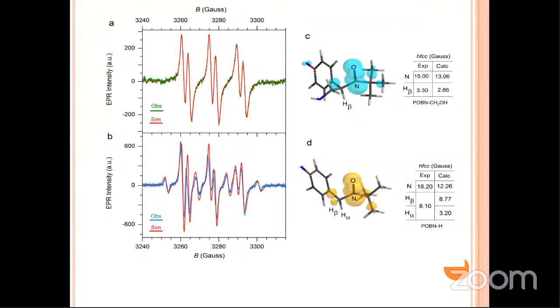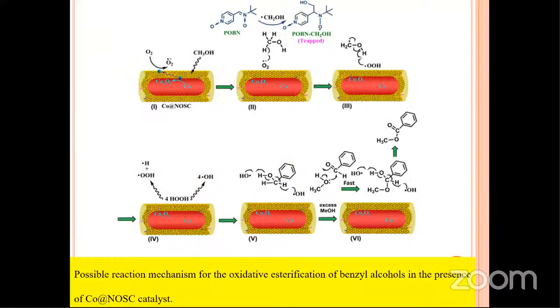Here we proposed a mechanism based on the characterization. We did an ESR, EPR study of the reaction media. We have trapped CH2OH free radical and H free radical. You know that in ESR, free radicals can be trapped by POBN. So we have seen the presence of hydrogen free radical and CH2OH free radical, and based on this ESR trapping, we propose how the mechanism proceeds.